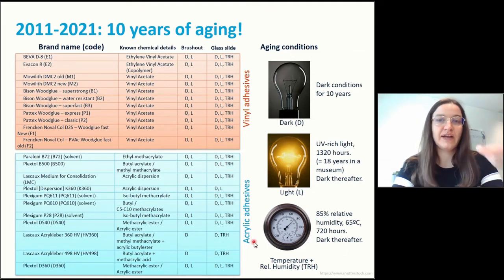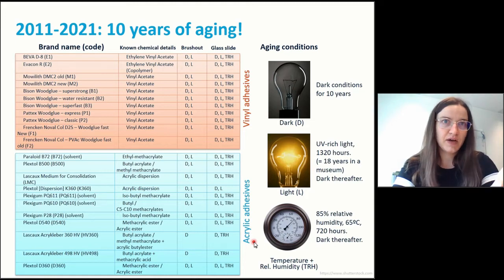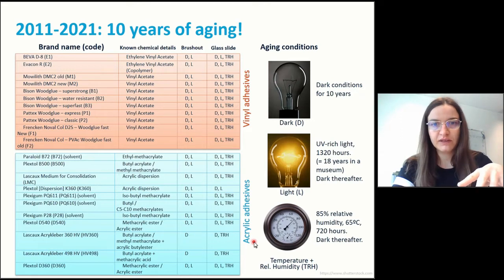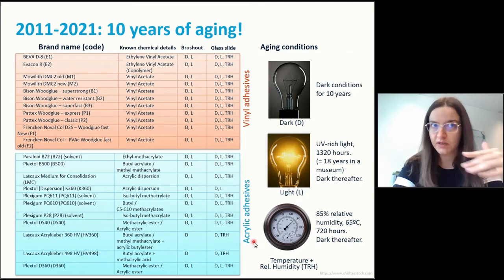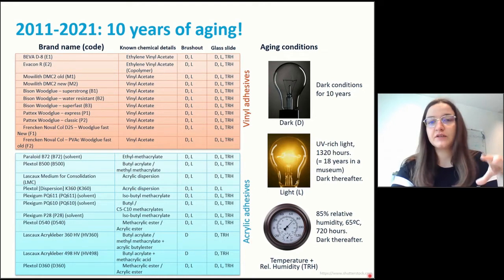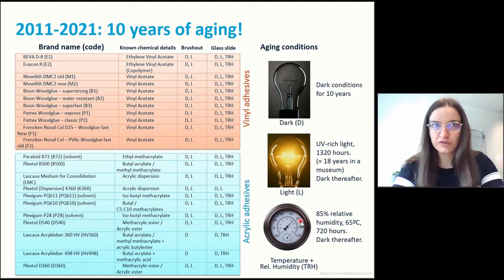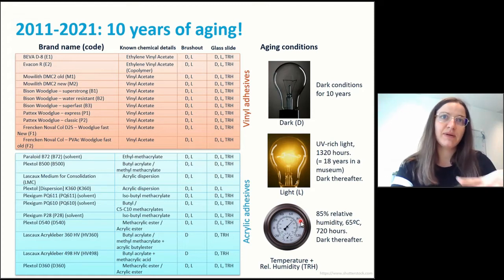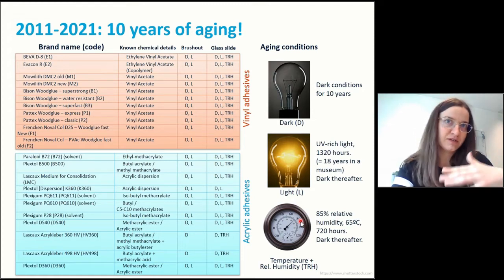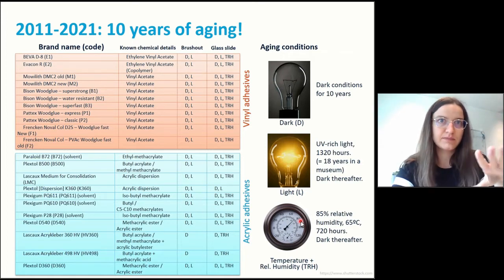These samples were exposed to 85% relative humidity and 65 degrees Celsius for 720 hours continuously. And then after this chamber treatment, they were put in the dark. So this was the initial treatment, and then afterwards we assume that the aging just went as it follows. This is supposed to reproduce conditions that are not lab conditions, but conditions that could actually reflect environmental arrangements that are different from standard scientific lab procedures.